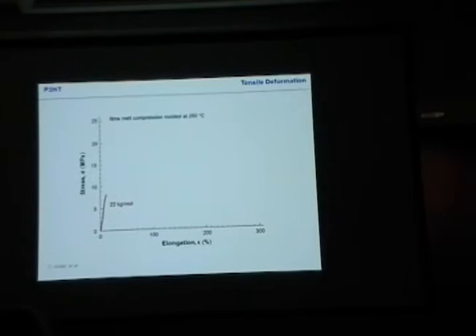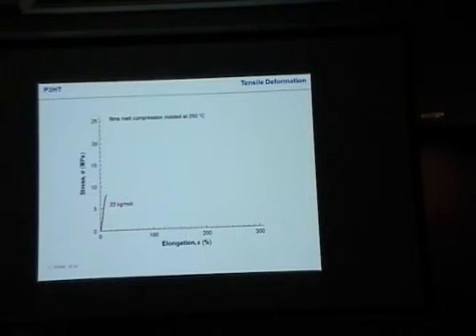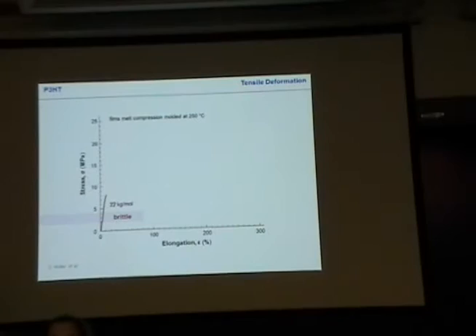And now we come to tensile deformation. The other very good tool — admittedly, with the amount of materials we usually have, not entirely simple — is tensile deformation. It's similar to viscosity. The mechanics — how much can I stretch a material before it breaks — depends on the amount of entanglements. When I don't have entanglements, you stretch it a tiny bit, so very small elongation when it breaks, nearly like a ceramic. It's brittle, because we don't have this interconnectivity between crystals.